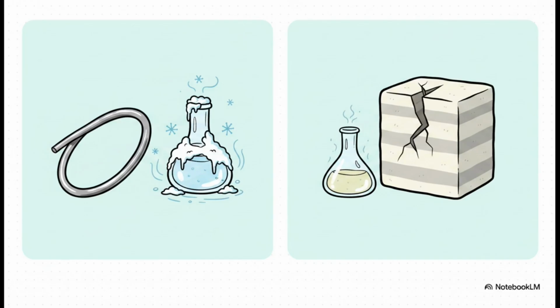Now look at high-temperature superconductors. The massive advantage here is an operating temperature of 77 Kelvin, meaning you can cool it with cheap liquid nitrogen. But look at its nature. It's not a metal, it's a brittle ceramic oxide, like ReBCO. It's fragile, incredibly sensitive to defects, and anisotropic. If LTS is a bendable metal spoon, HTS is like trying to bend a ceramic coffee mug. This brittle ceramic reality is the very first clue in our mystery.